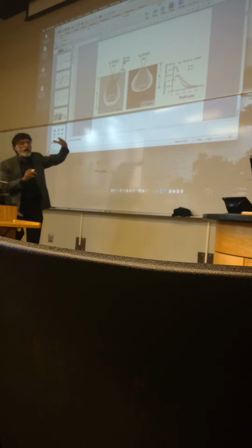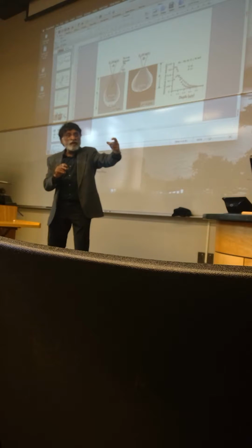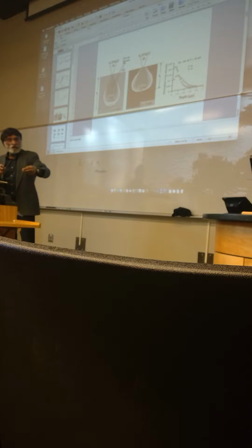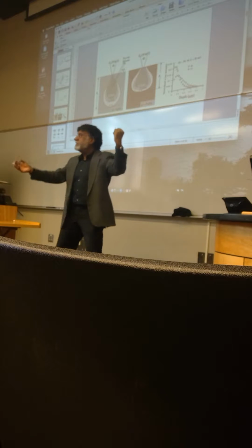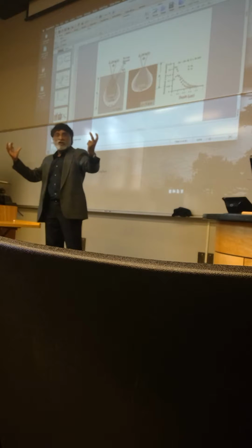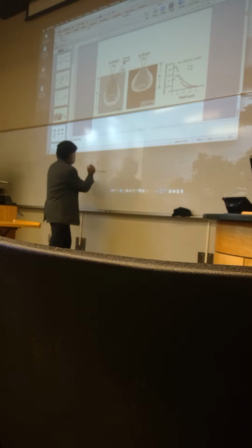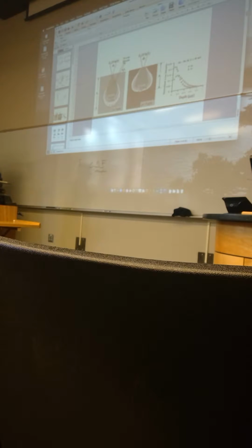But X-rays of a higher energy can also be used to excite X-rays of lower energy. So if you have a K line, which is at 20 kilo electron volts energy, it can always excite an L line at say 5 keV. So this process is called fluorescence. So the intensity is also going to be affected by all these parameters: the atomic number, which tells you how much the incident electron is propagating in, the absorption of the outgoing X-rays, and the fluorescence.